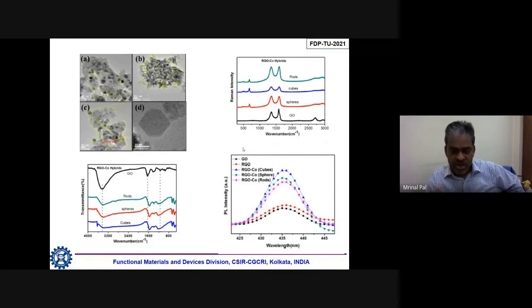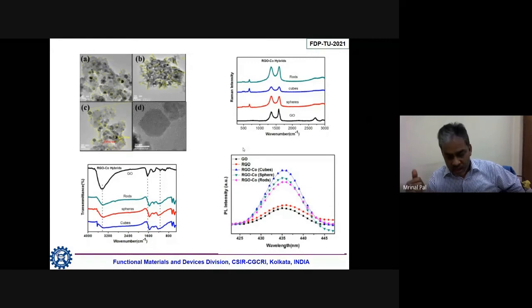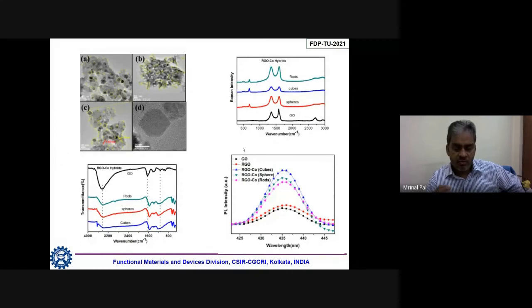It is possible to change magnetic properties. In our earlier work we have shown that. In this case we are showing that again this luminescence property, particularly the blue emission, can be tuned, the intensity of blue emission can be tuned, and it can be enhanced by again changing the morphology, and we got maximum blue emission in the case of cubes only, cobalt cubes.